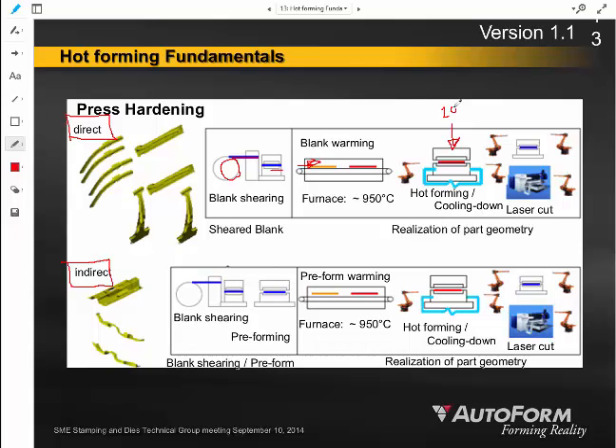Something in the ballpark of 200 to 80 degrees C, right? When you get this material down into the range of 200 degrees C to 80 degrees C, you've already cooled it sufficiently that it's going to have the appropriate microstructure. Then potentially you could use a robot to gingerly unload that blank, let it go down to the conveyor belt so that it can get racked, or bring it to another station for laser cutting, laser trimming. Right? This is what we would call direct press hardening or direct hot forming.